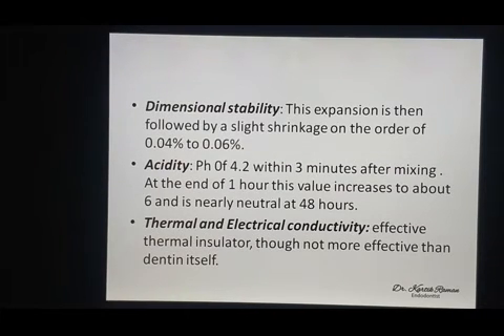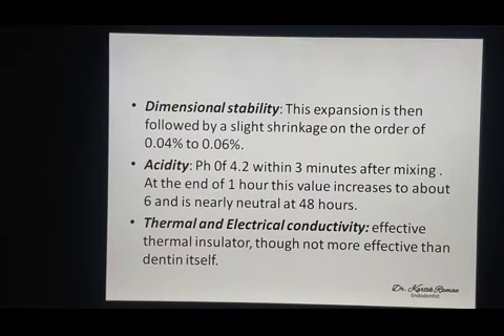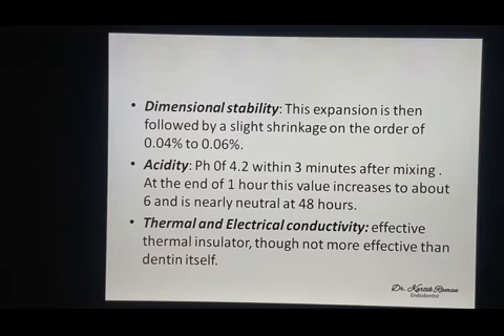So the pH just 3 minutes after mixing goes to 4.2, so it's a very, very acidic cement. Remember, cavity varnishes were very commonly used prior to application of zinc phosphate as a base, and then on top of the zinc phosphate, after it set, silver amalgam was used, and it's a very effective thermal insulator.